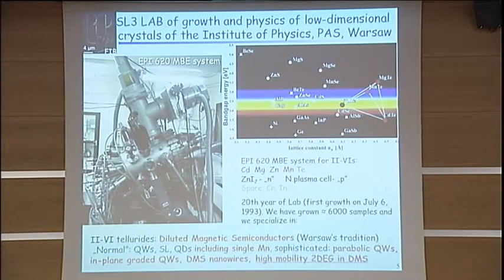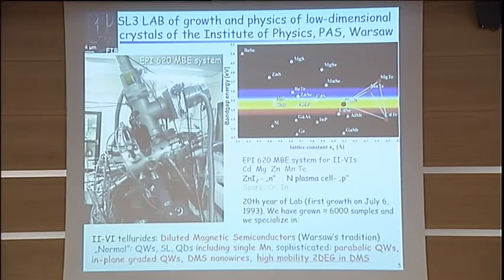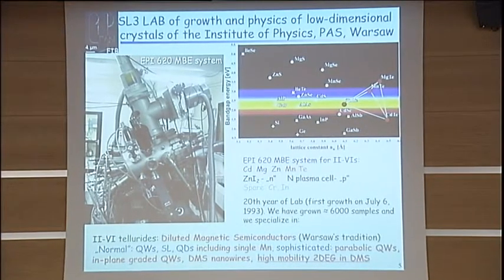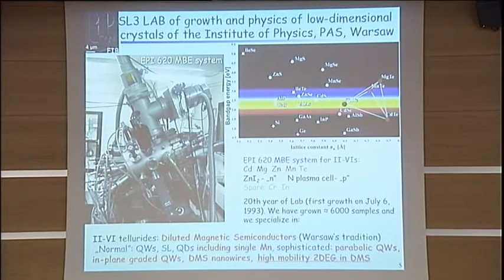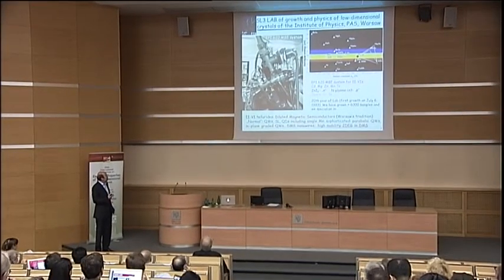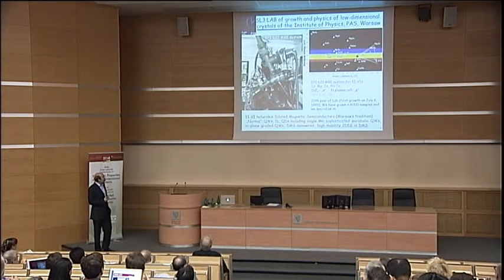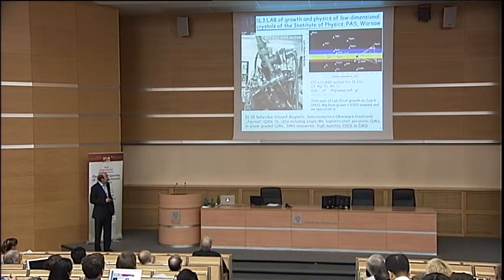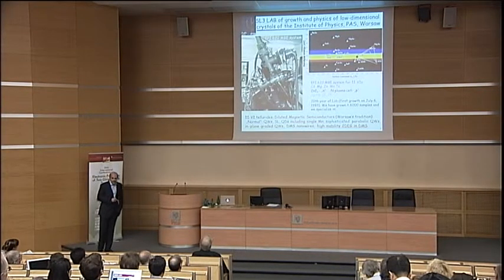And how can one grow those kinds of structures? Of course, the best known and the most useful method is molecular beam epitaxy, and this is how we grow those structures in our Institute of Physics. And we have a very small American company EPI now Veeco MBE chamber with 6 ports, so we can only grow materials in these triangles: zinc telluride, cadmium telluride, manganese telluride, magnesium telluride. And actually tomorrow, on July 6th, will be the 20th anniversary of our first growth.